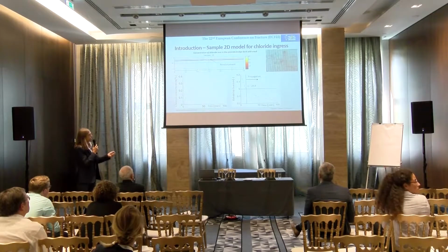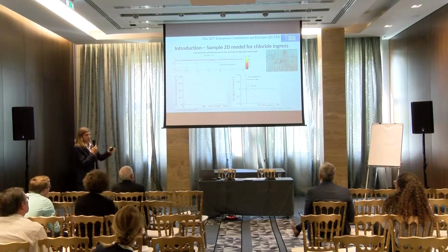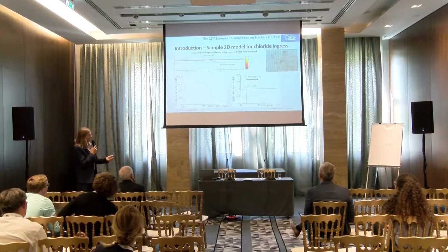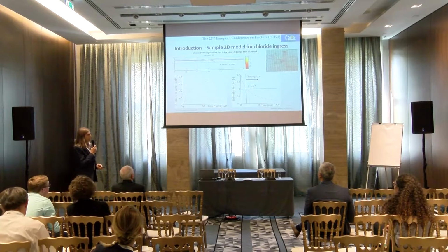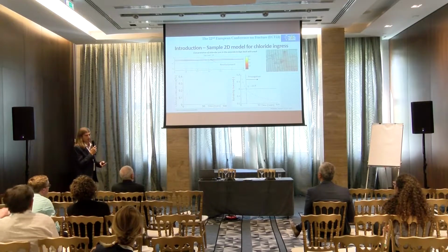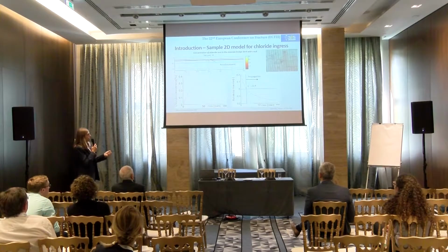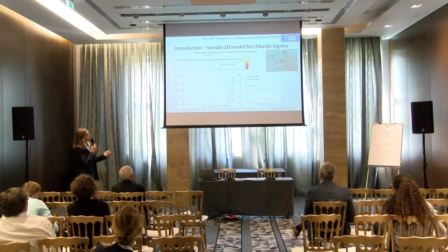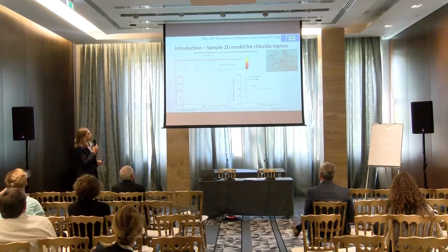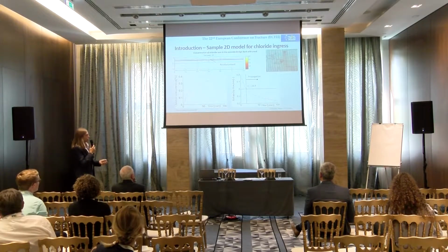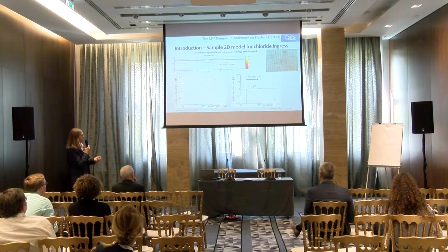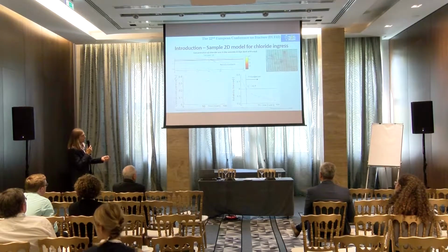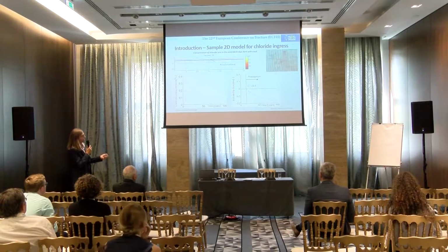And this is a surface of, for example, bridge deck. So this is the vertical cross-section of the bridge deck. And for example, this is the picture from the US highway bridge deck, and the concrete is prone to cracking. So this model can handle also the ingress of chlorides via the cracks to some extent. And those two pictures are illustrative. The chlorides concentration increases at the reinforcement level over time, and then here is the other way around. We compare when the chloride concentration is at the unacceptable level and the corrosion propagates.